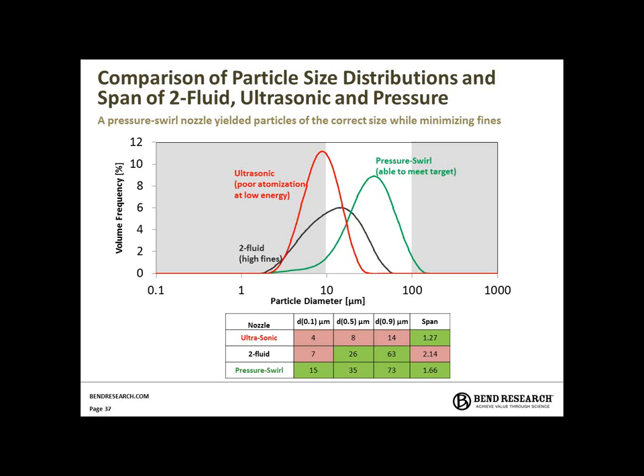Slide 37 shows some of the actual particle distributions produced with these different nozzles. So with the ultrasonic, you can see a very tight span, which is well known to these ultrasonic nozzles, but the particle size, there wasn't enough tunability in the energy inputs for that atomization method to increase the particle size much higher than what's shown.